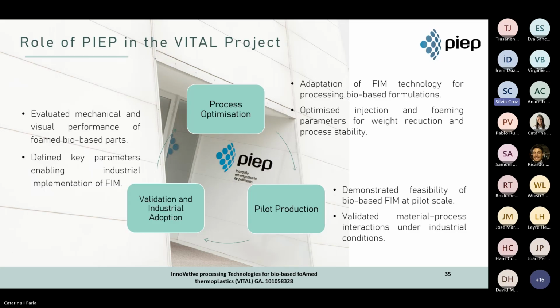Through experimental trials, digital modeling, and collaboration with partners such as Edener, Arçelik, Tofas, and Farplast, PIEP contributed to the adaptation of the foam injection molding technology, processing bio-based formulations, and process optimization, demonstrating the feasibility of the use of the bio-based material at pilot scale. It validated material-process interactions under industrial conditions, evaluated the mechanical and visual performance of the foam bio-based parts, and defined the key parameters to enable industrial implementation of foam injection molding.